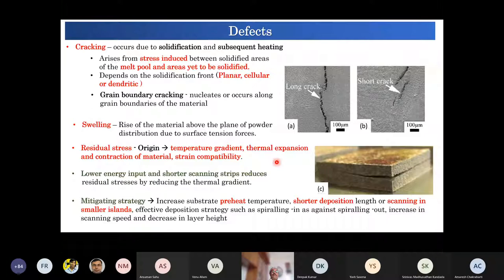Then the residual stresses are very, very important in engineering products. Even in the case of normal cast and wrought products, residual stresses have to be minimized and controlled. And here, because of the very large solidification rates or very fast cooling rates, it is inevitable because of the thermal gradient, and it is also on the substrate. So all that leads to some kind of residual stresses in the material. To reduce the residual stresses, lower energy input and shorter scanning strips are required. But again, it has to be weighed against the requirement of the process.